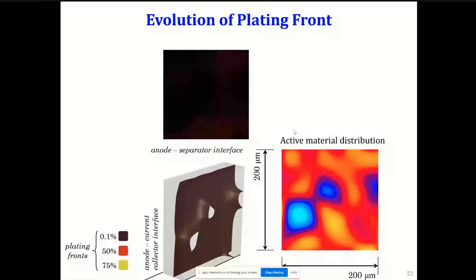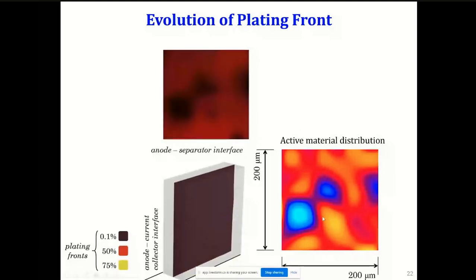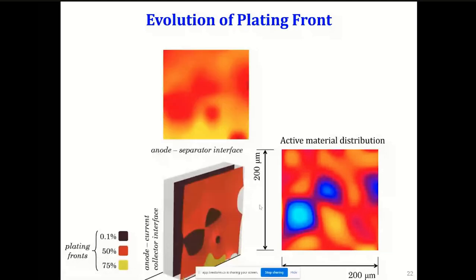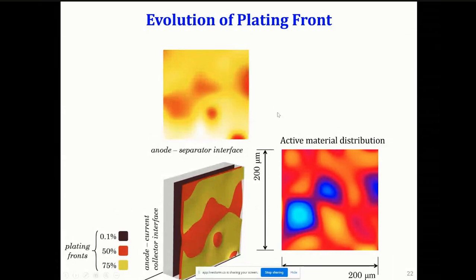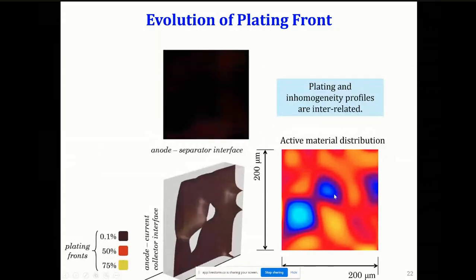Now, let us look at what happens to plating. So this is the reaction that happens on the negative electrode, which is the anode. And what I'm showing you here is how this front of plating starts depositing from the separator. And see, the initial distributions are mapping the active material distribution that you see on the right. But as time passes by, you start seeing more and more different patterns. And this comes because the necessary driving force for this reaction comes from the intercalation, which is the primary reaction. So it sets the voltages that are going to drive the second reaction, and it will also set the local availability of ions that would participate in this reaction. So that's why this plating inhomogeneity would be related to what your active material distribution is.